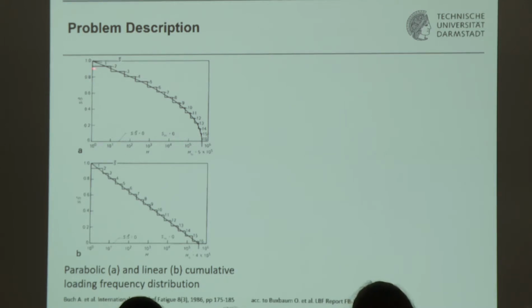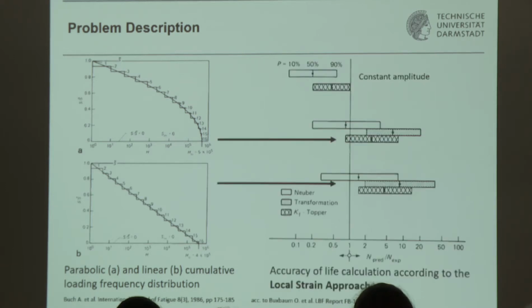for example, these cumulative spectra of exceedance of some levels, maybe a parabolic shape, which is common in the automotive industry, or a so-called straight line shape, which is characteristic, for example, of offshore applications, then you may want to perform a prediction of crack initiation life with a local strain approach. And at that time, and still, you see results which are detrimental in terms of the number of predicted cycles to crack initiation compared to the experimentally determined cycles to crack initiation.